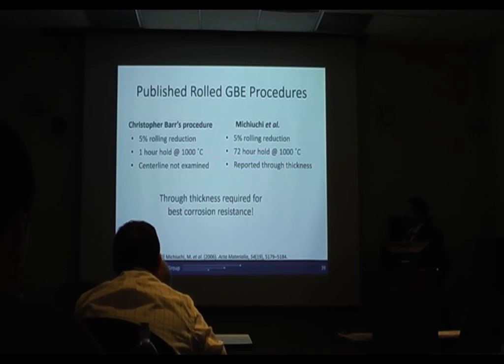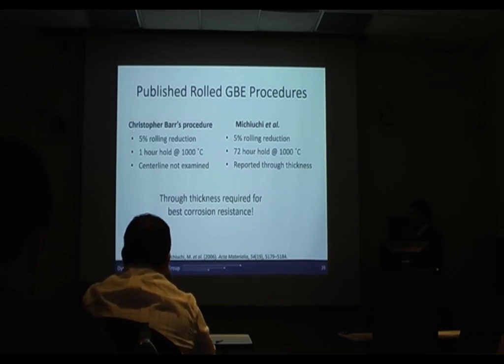So Dr. Barr's procedure, which he spent quite a bit of time refining, he settled on a 5% rolling reduction and then a 1 hour hold at 1000 Celsius. However, he did not look at the center line. Michiuchi used a very similar procedure, except that he held for 72 hours. And he reported that he was able to, by doing that, propagate through the thickness. And again, we wanted that for the best corrosion performance. However, when we attempted his procedure, we found that it was significantly more variable than we would have liked.